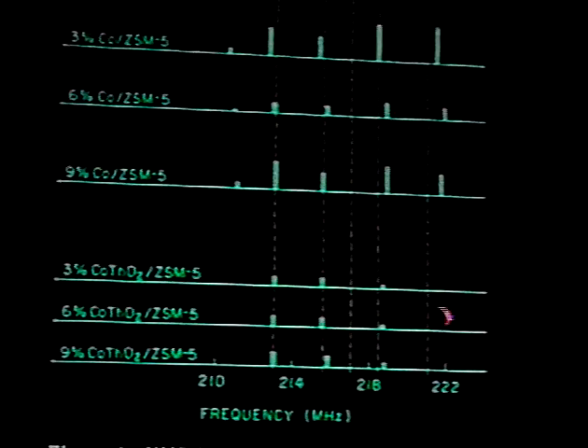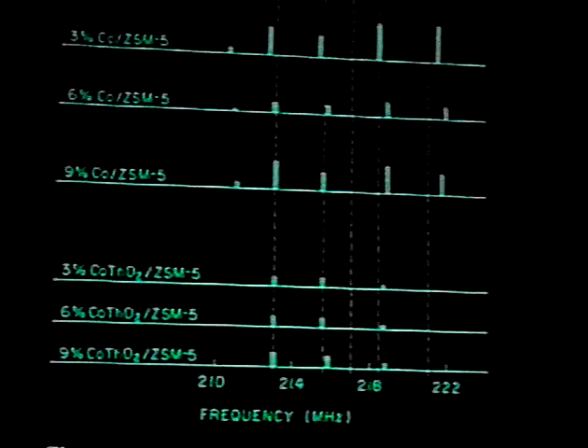Now when you go down to small particle size as in cobalt thoria, you almost are reduced to single domain particles. The typical magnetic domain size of cobalt is about 100 angstroms, so you are down to single domain particle size, and therefore the number of domain walls is considerably reduced, and this results in a reduction in the NMR intensity.